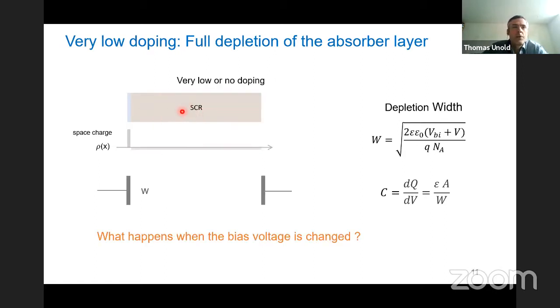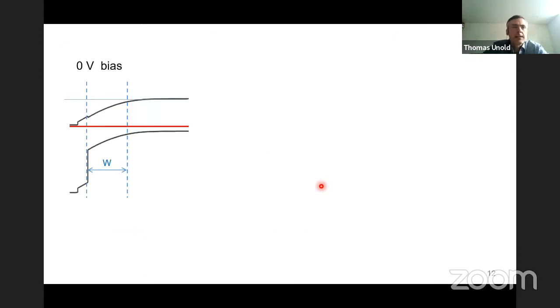Now, if you have very low doping, again, this should be a sharp charge balance here. I don't show this so well because this would have to be higher, but basically this charge has to balance the one on this side. And so what happens if you have very low doping or no doping is that your whole device is depleted. And then your contacts form your capacitor. And then you could already think, so what happens if I change the voltage now? The measurement becomes kind of complicated. So I'll show you that in the next slide.